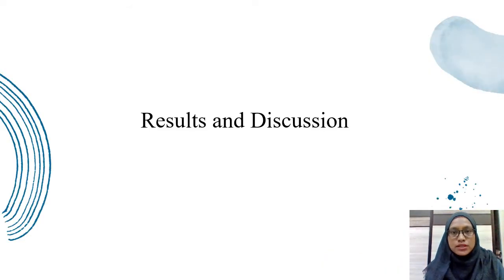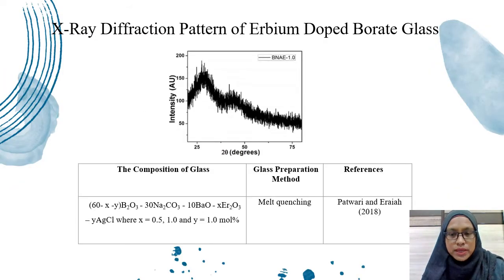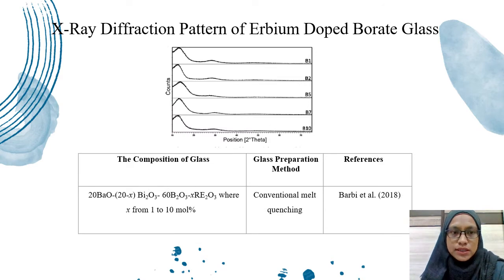Result and discussion. XRD pattern by Patwari and Eraiah shows that there are no sharp peaks, instead a broad peak. Barbi et al. XRD pattern shows no sharp peak, which indicates that bismuth borate glasses are amorphous in nature.